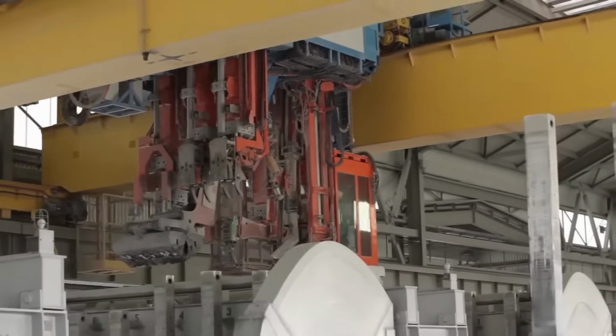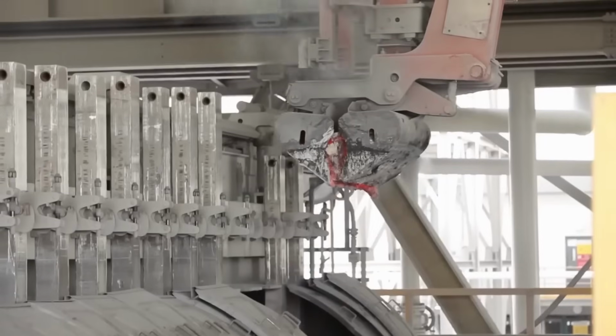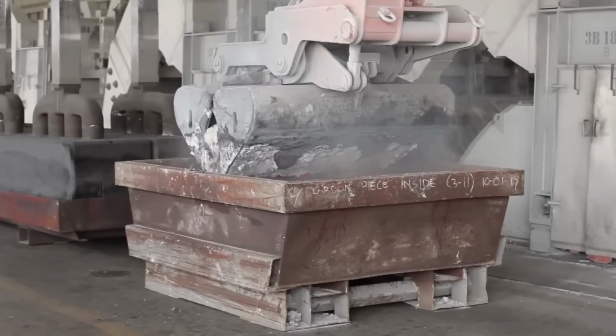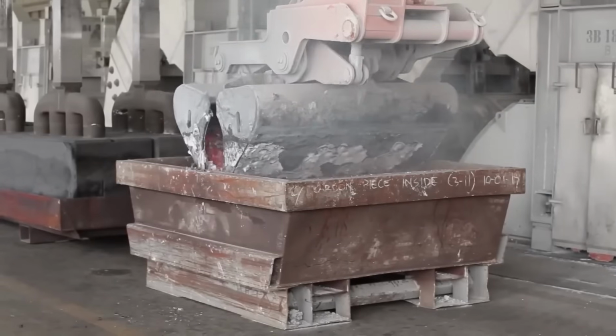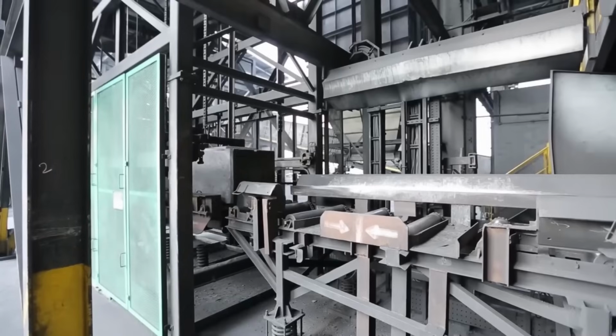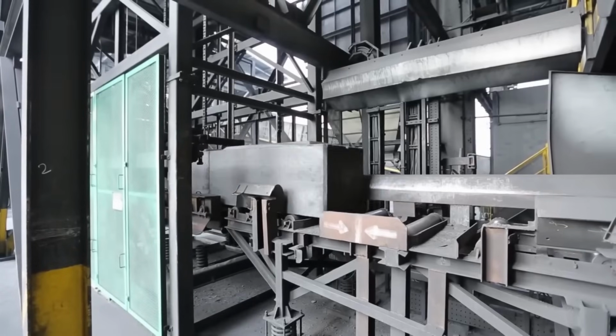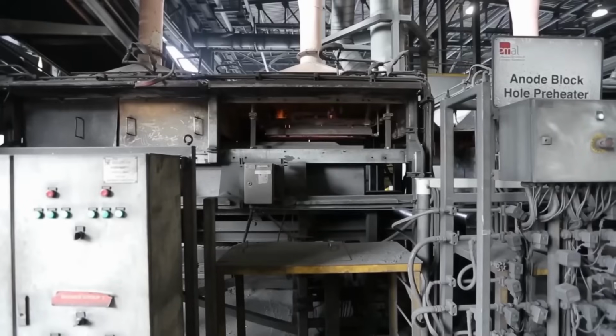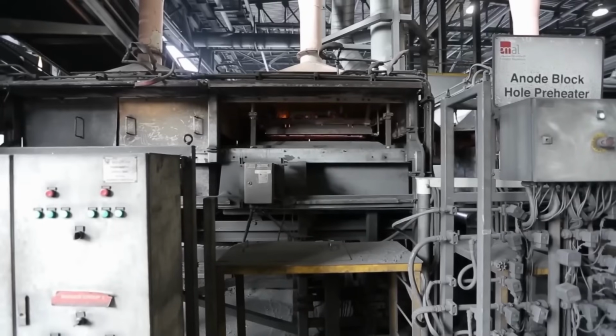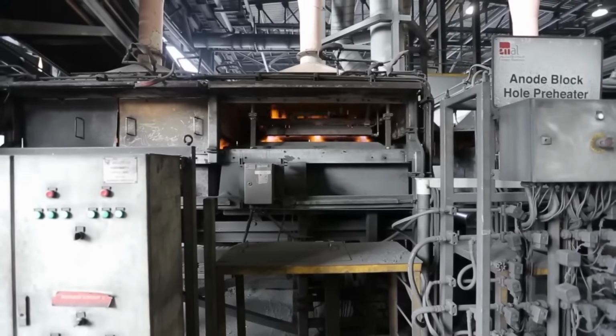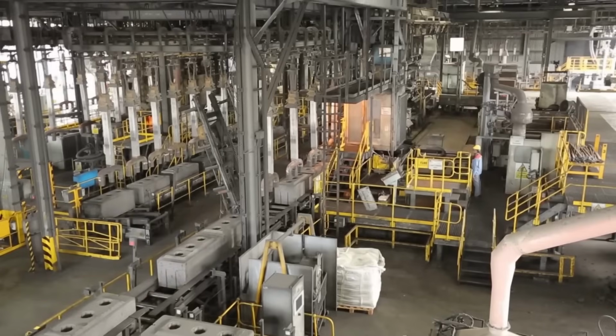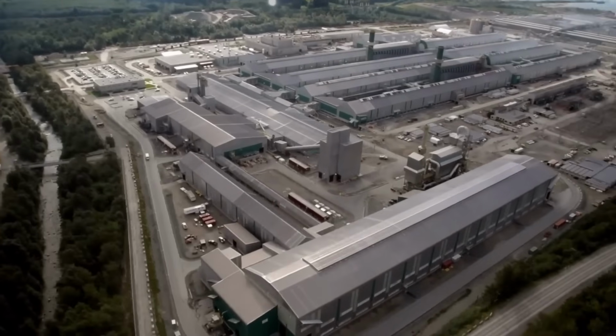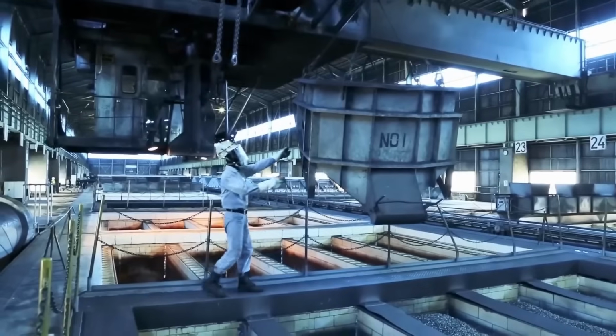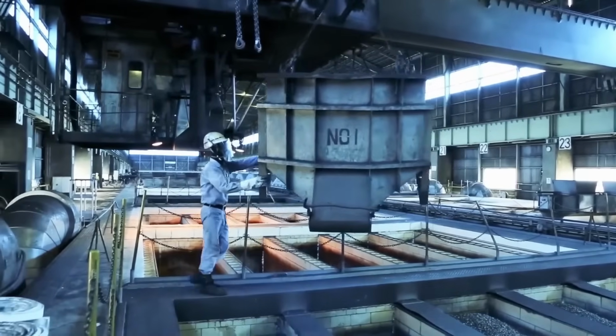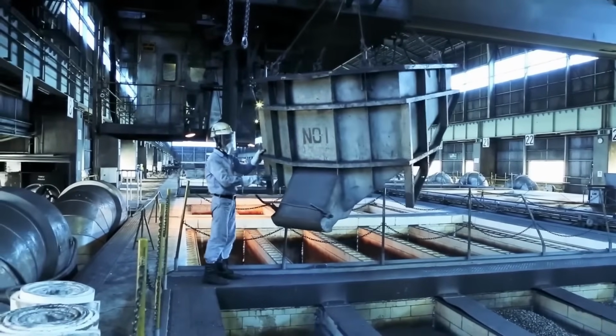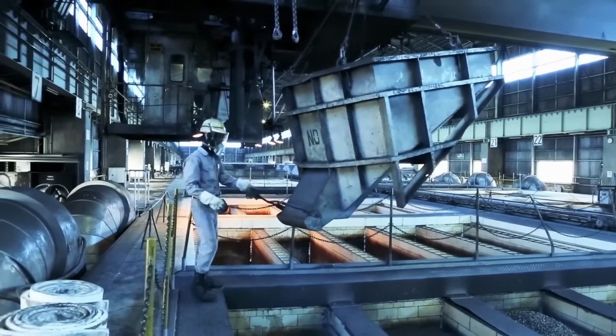Inside each cell, the electric current splits the aluminum oxide into its elements. The aluminum atoms break free and, being denser than the surrounding liquid, sink to the bottom as molten aluminum. The oxygen atoms released in the process don't just vanish, they react with the carbon anodes to produce carbon dioxide gas. This step is a major source of emissions for the industry, and it's one reason why researchers are now working on carbon-free anodes that could cut these emissions dramatically in the future.